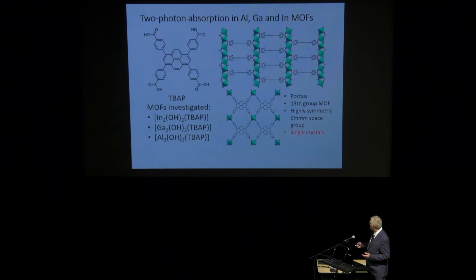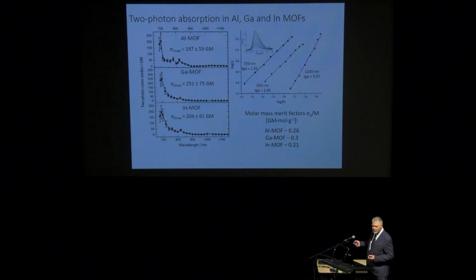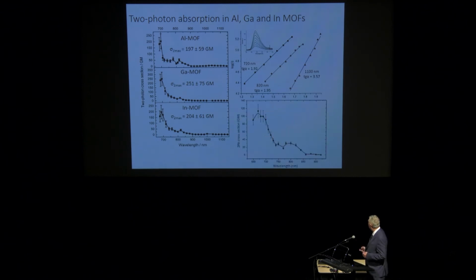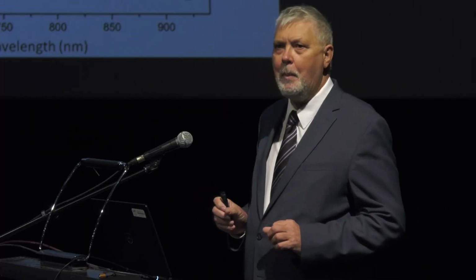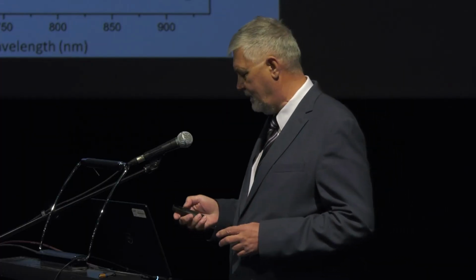And this is an example of work in which we used a certain ligand, which is already a good 2-photon absorbing molecule. And these are 3 different MOFs containing 3 different ions. And as you can see here, there's not really much of a difference in the cross sections for these 3 MOFs. And moreover, there's not much difference between the spectrum of these MOFs and the spectrum of the ligand itself. So no, we don't really have much of the enhancement in this case.